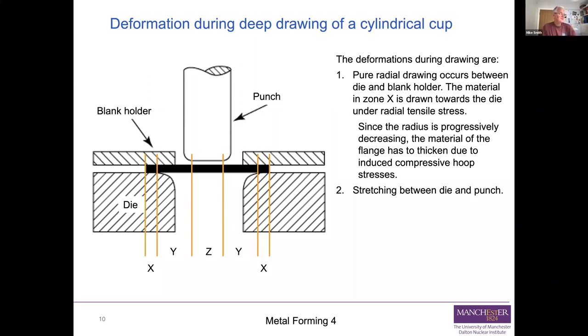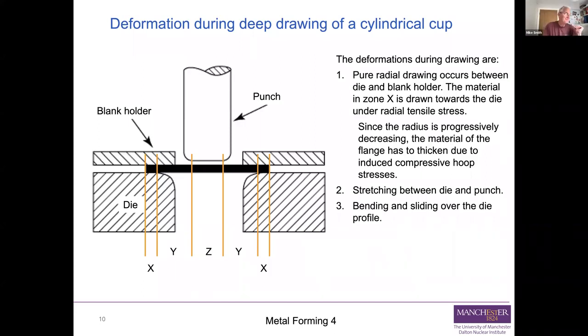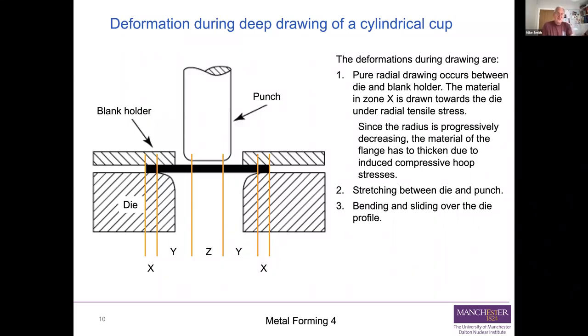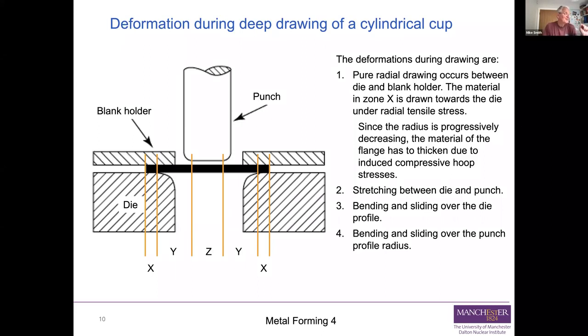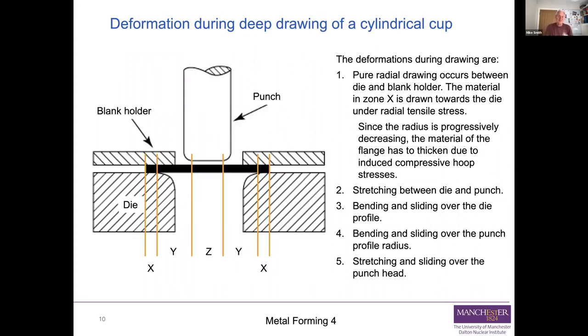Once the material reaches the die edge, you can stretch it, then bend it over the die profile as it's pushed down and bending around that very rigid die. The material slides over that die profile as it's pulled down into the cup - it has to go round the edge and down into the cup to form those tall walls. The same bending and sliding happens at the punch profile radius. Underneath the punch, the material is simply stretching radially, which means it's getting thinner, and on average flowing out from the edge of the punch and up into the walls.